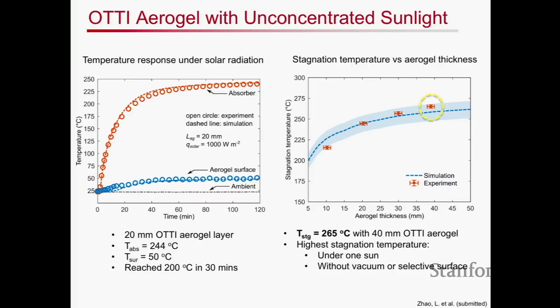So here, what you're seeing is the temperature as a function of time. This is an ambient here. This is in a controlled environment in a lab first. And you can see that the aerogel surface is still relatively low here, but meanwhile, the absorber surface is reaching relatively high temperatures, exceeding about 220 or so degrees Celsius, right? And what we've been able to also show is that we can reach stagnation temperatures.